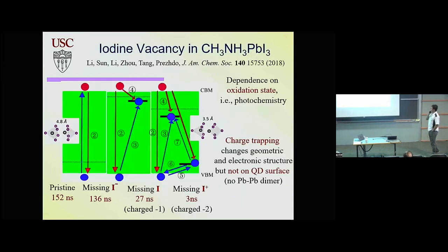Now the chemical part, the missing iodine. You have a vacancy. A vacancy by itself does not create a trap state. But if you start putting charges through the device, charges can be trapped, and if you trap a charge, you create a new species. If you remove an iodine, you have two leads that are left out. If you put an electron between them, you have lead two plus and a negative charge in the middle. The charge binds those two leads together, so you make a new chemical bond. And when you make a new chemical bond inside this material around the defect, you create several mid-gap states.